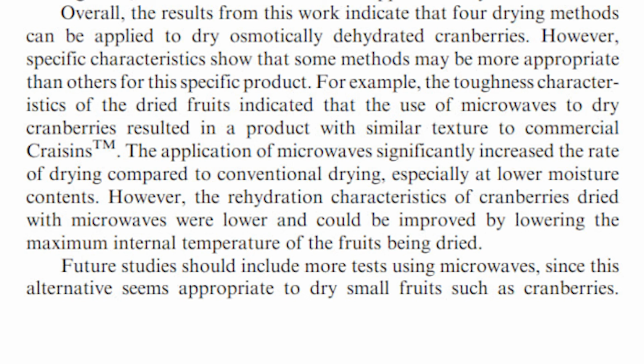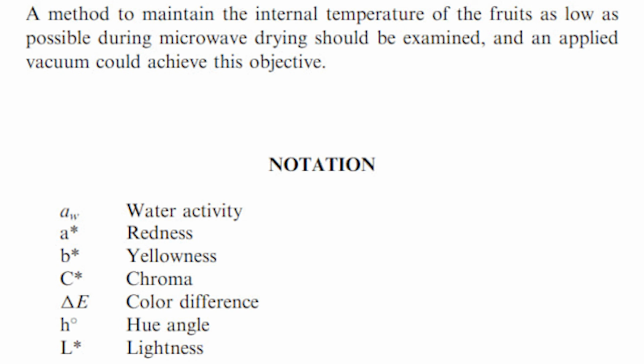The application of microwaves significantly increased the rate of drying compared to conventional drying, especially at lower moisture content. However, the rehydration characteristics of cranberries dried with microwaves were lower and could be improved by lowering the maximum internal temperature of the fruits being dried. Future studies should include more tests using microwave, since this alternative seems to be appropriate to dry small fruits such as cranberries. A method to maintain the internal temperature of the fruits as low as possible during microwave drying should be examined, and an applied vacuum could achieve this objective.